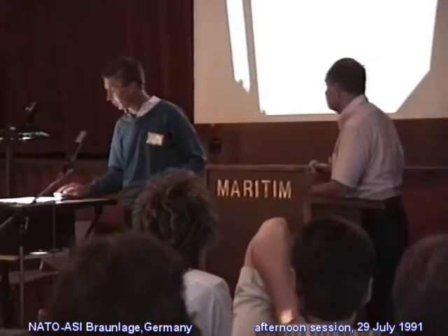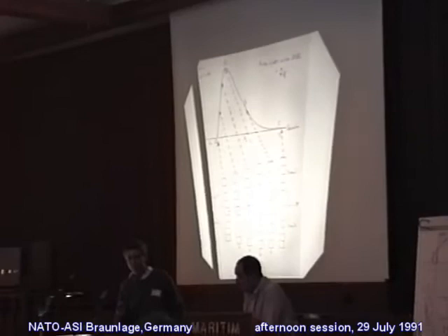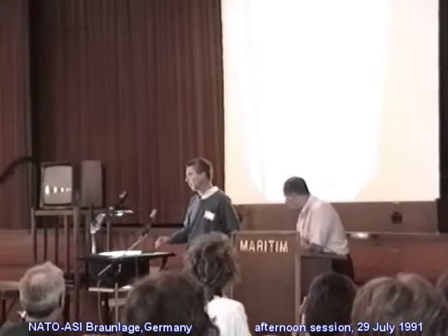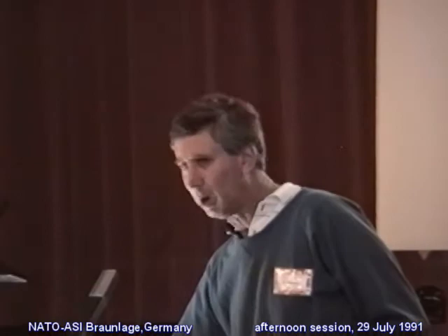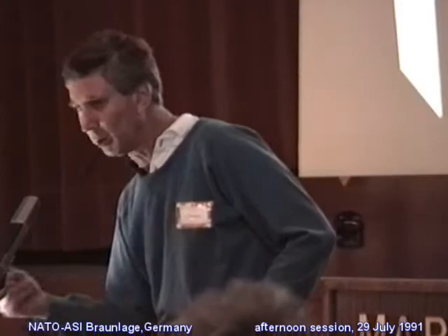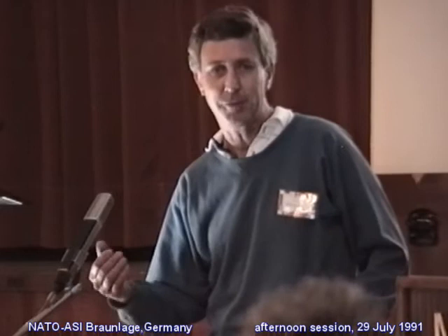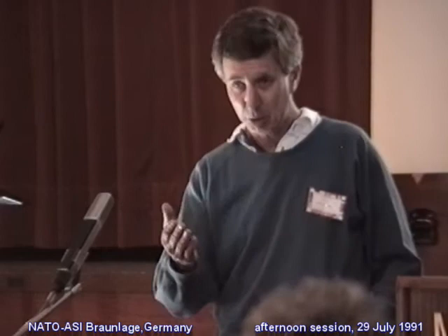Something perhaps like silicon or diamond, where the bonds are very localized. And I think in the picture that Jacob was trying to present, as we run a crack through such a system, we pop bond by bond, and therefore we emit sound waves. But there's also, in most of these systems, since we're doing it at room temperature or at elevated temperature, thermal fluctuations as well. And although there can be very local energy barriers to overcome as we go from one bond to the next and allow the next row of bonds to take up the strain of a predecessor, thermal fluctuations can help if the energy barriers are not too large. And this will certainly be the case with materials like mica, where the bonds are not so strongly localized as they are in silicon and germanium and diamond.